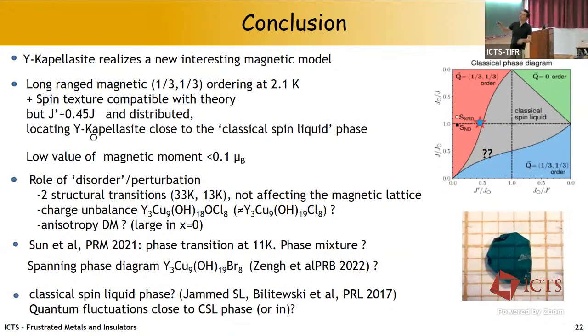So let me briefly summarize. We observed the long-range order with a spin texture and wave vector that are compatible with the theoretical prediction for the nearest neighbor model. We observed a very small moment, probably related to the proximity to the boundary between the two phases.